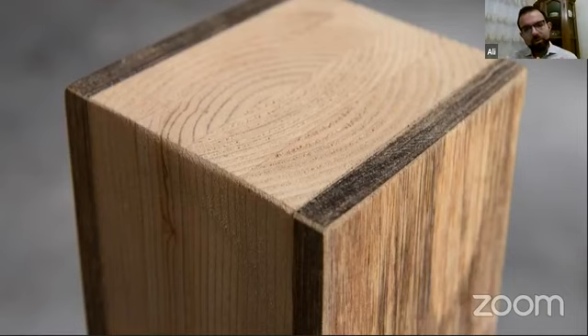So what we did, we said, okay, if you don't want to use the whole section out of glulam, you could use part of it out of glulam and then reinforce it with our materials. Again, the results were quite promising. We were able to achieve a 20 to 25% increase in mechanical capacity, especially in elastic modulus in terms of deflection. So this was the idea on how we can promote our bamboo composite materials, especially in countries like Singapore that are a bit reluctant to use anything related to bamboo.